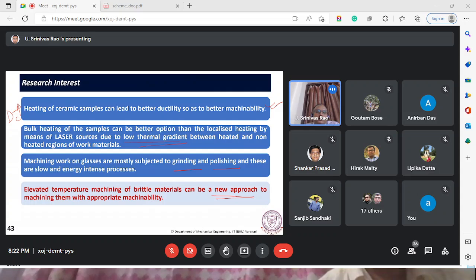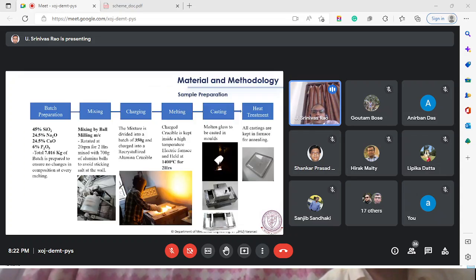In that, one PhD scholar has worked in this area. Before going into that, a little bit of information about the sample preparation of bioglass. This indicates the material composition which is taken, and to keep all the specimens of uniform composition, at once the total material is prepared, so it goes through this mixing of the powders.